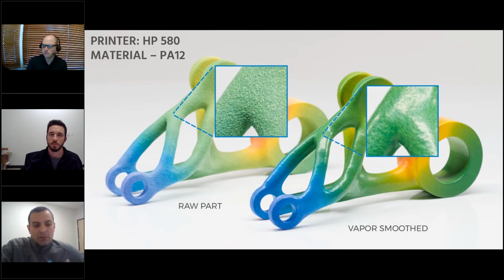So sometimes a part breaks not necessarily because the material properties are poor, but because you have all these imperfections at the surface. And that's what our process does. It really focuses on healing the surface of the part in a very automated and very controlled way, so that we can get rid of all those crack initiation sites, all those micropores that, although they may not look significant when you're handling these parts, when you inspect them under a microscope, you can understand how and why these parts break. So by being able to seal them and erase all those imperfections, what we are doing essentially is improving any of the properties that will be dependent on a micro crack initiation at the surface.